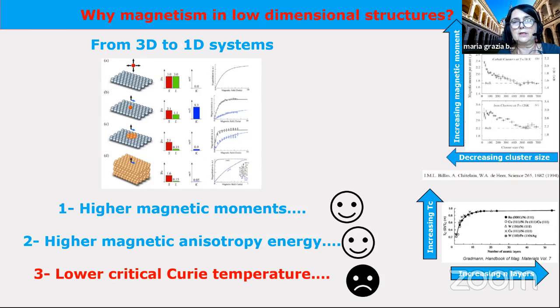And then if you look at the important magnetic anisotropy energy, we can see that if you have a single atom, we will have an isotropic system. If we put this atom on a surface, you will increase the magnetic anisotropy energy. This example is of cobalt on a surface. And then if you put a cluster, you will have another increase of anisotropy energy. And then you can compare the cluster with the bulk. So in a bulk of cobalt, it is not isotropic, you have an easy magnetization axis, so a preferential direction for magnetization.